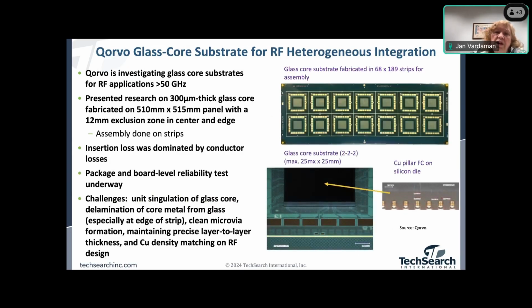So Qorvo has done a lot of work in looking at this for an RF solution. Basically, they have a glass substrate core that's fabricated in 68 by 189 strips for assembly. So this is for RF applications that are greater than 50 gigahertz. They presented some of their research on a 300 micron glass core that's fabricated on a 510 by 515 panel line with a 12 millimeter exclusion zone in the center and the edge. Assembly was done on strips.